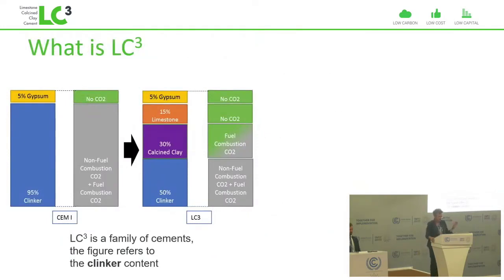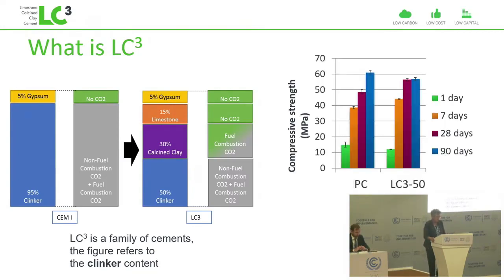On the left here we have the composition of a classic cement and the associated CO2 emissions. We have most of the emissions coming from what's called the clinker. And in LC3, we replace at least half, and we can replace even more than half, but at least half of that material by the calcined clay, which has much, much lower CO2 emissions, about 1/10 of that of clinker, with limestone with no CO2, and with gypsum. And the nice thing is that we don't lose anything in terms of performance.